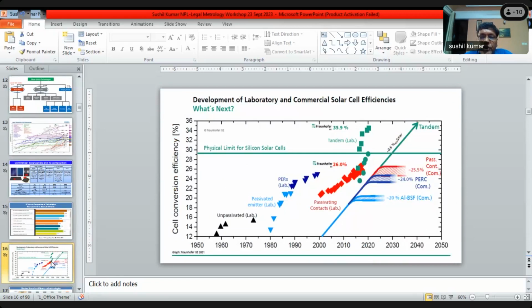And as for the progress in the technology, in the commercial cell efficiency, starting from 1960 till now, earlier it was all unpassivated solar cell. Basically whenever the light gets absorbed, electron hole pairs are created and they get lost in the recombination process, so passivation at the surface is needed. Earlier that technology was not there, so efficiency was poorer, but once people started learning about passivation, during the 1980s or so, then the passivated emitter solar cells came in, and then the PERC solar cell. This is also the passivated emitter rear contact, the back contact, because maximum loss comes in the back contact. And then other advancement in the technology came, the TOPCon and others.